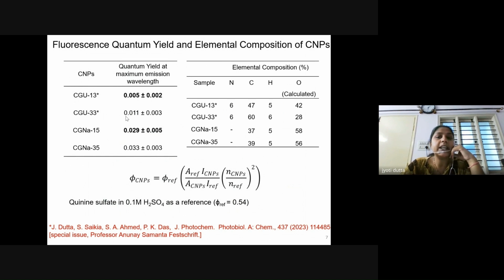Now, if we further check the elemental composition of these carbonaceous nanoparticles, we observed that the composition of the carbonaceous nanoparticles which were prepared using glucose and urea showed a significant variation, though they were isolated from the same reaction mixture. You can see the oxygen content as well as the carbon content for these two nanoparticles varied a lot. For our purpose, to explore these nanoparticles further, we wanted to have a consistent elemental composition so that we can correlate their fluorescence properties with their composition and with their sizes, keeping the composition constant. So in the first set of carbonaceous nanoparticles, where we were using glucose and urea, the elemental composition varied a lot, though these two carbonaceous nanoparticles were obtained from the same reaction mixture via filtration.